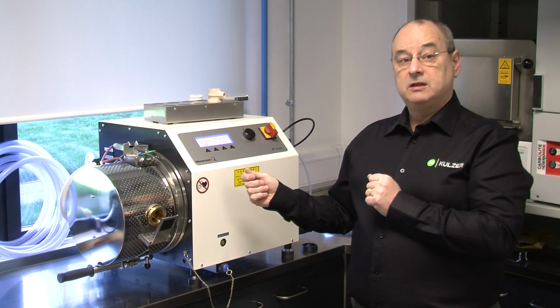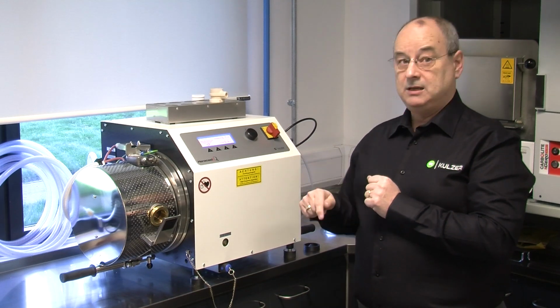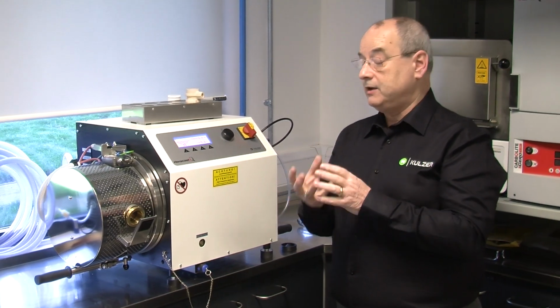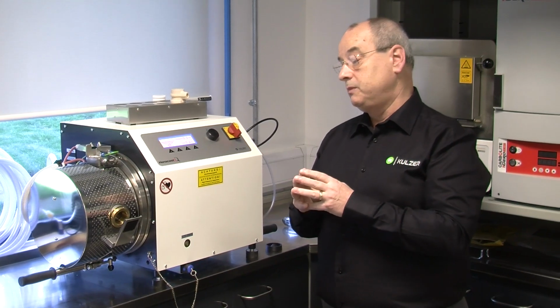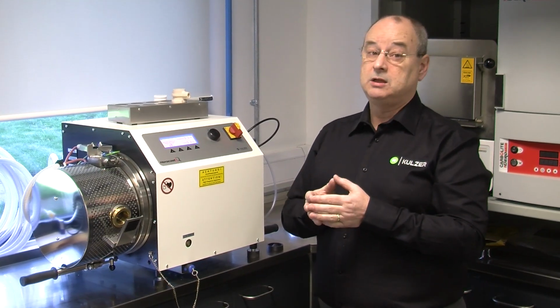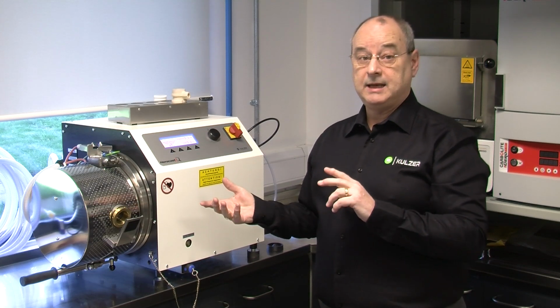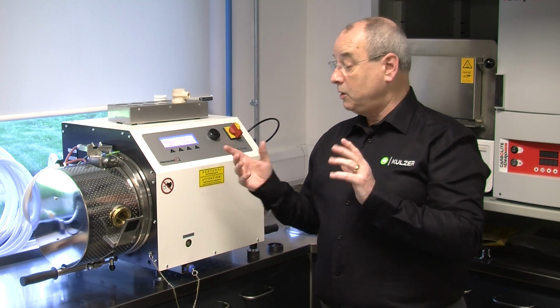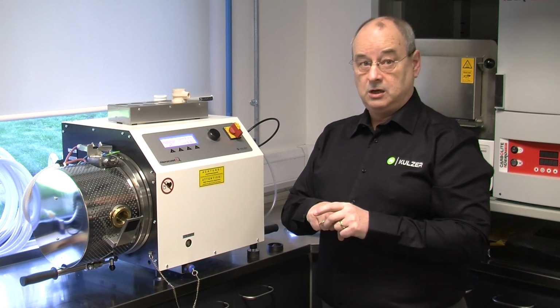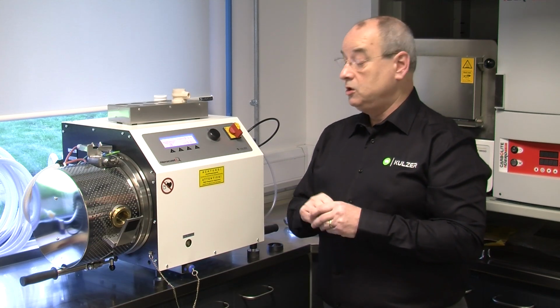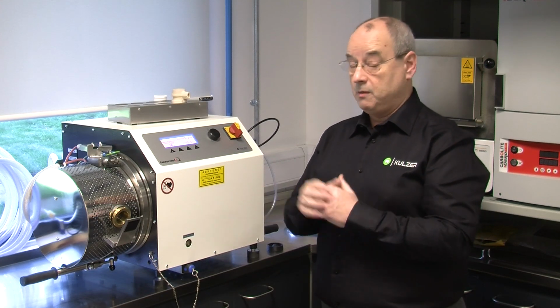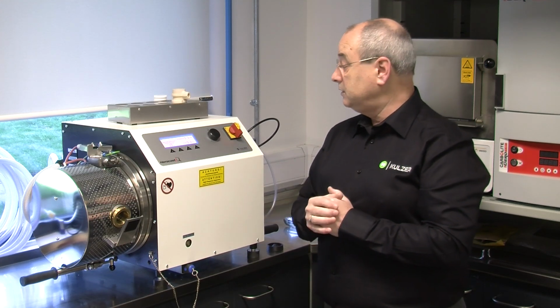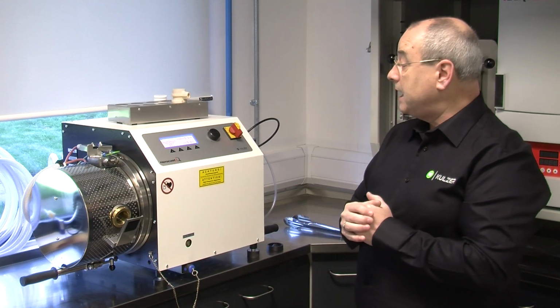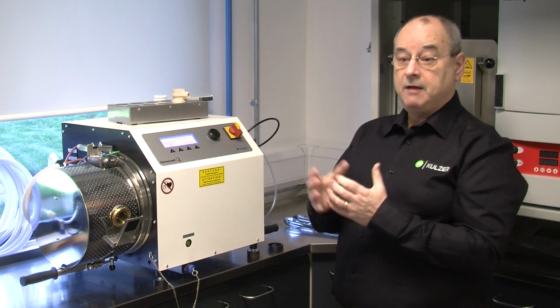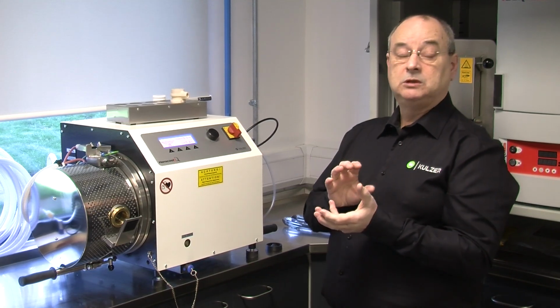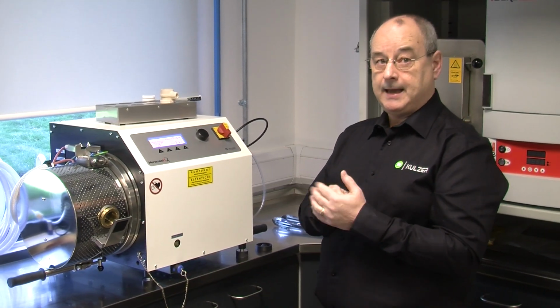The air is now coming in, so the vacuum eradicates and air comes into the chamber. We do not have a suction part, and this is where it changes from your normal centrifugal casting situation to a tip and pour technique. It purely is gravity. So if the alloy is not into the casting ring quick enough, then you can have problems with miscasts, which we'll come on to with the sprueing technique, which I'll show the technicians here. It always stays down for a minute so that everything is solidified under pressure, so it's the most dense and accurate castings you can get.